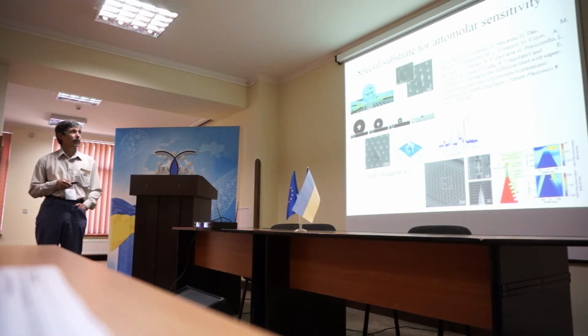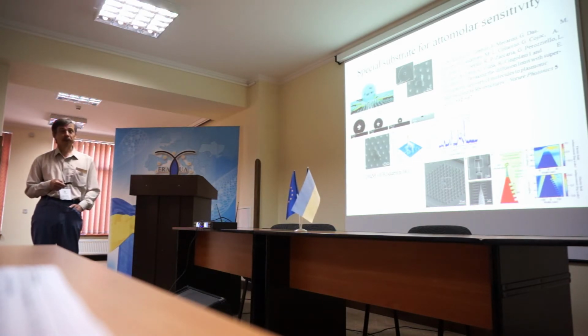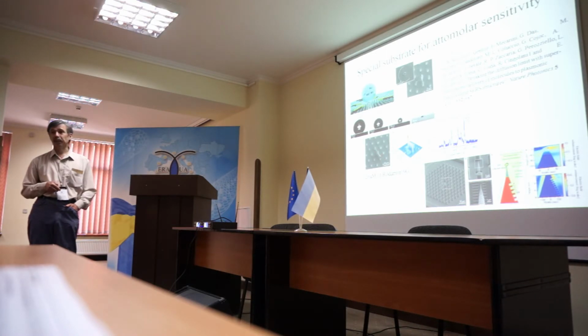Because this surface is practically absolutely hydrophobic, you may see that he deposited a drop of analyte on the top. This is the size of this drop at the beginning. And during the evaporation of the solvent, this drop doesn't spread over all this area, but it shrinks and jumps from one pillar to another until it is already not a solution. And only in this last final step, it will leave the material which is dissolved there in such an area. You may see that the rest of this drop, with only 20 attomolar of rhodamine, was left only on 3 pillars.